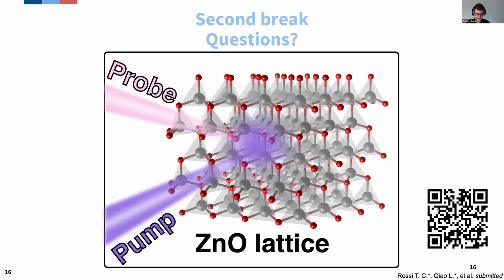So we believe that this approximation that we have made of splitting this into two contributions becomes less and less valid as you go to softer edges. And the reason for this is because we are observing core excitons. So these are very small particles. And we think that they couple very little to the atomic motion. So when you are dealing with core excitons, if there is lattice heating taking place, they are barely affected by that if it's an exciton at the K edge of a transition metal, for instance.